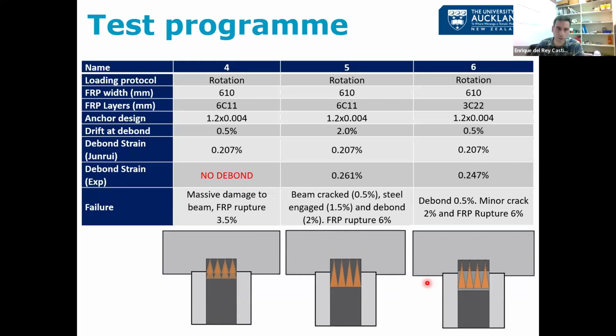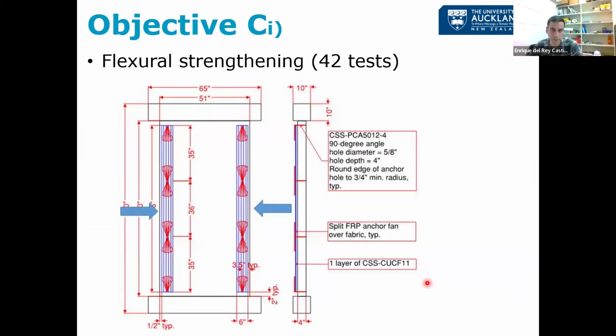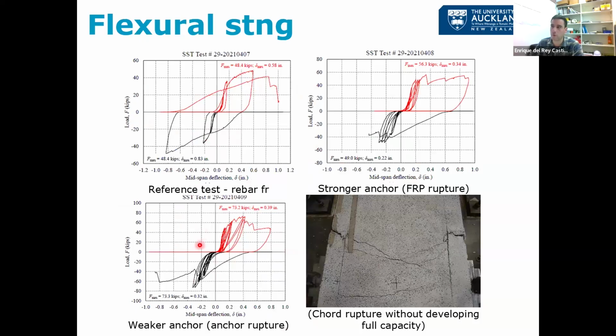Then we are leveraging some tests that have been done by our partners overseas on flexural strengthening of slabs. So these are, from the top of my head, I think they are 4 meter long slabs that were strengthened in flexure. So the flexural steel is not enough, and we are applying FRP, different anchorage configurations, 42 tests. And basically, this is giving us an idea of how we can increase the moment capacity of that slab or of that diaphragm without compromising the ductile response. We don't want to increase the force, the moment, but then have zero ductility, a very brittle response from the floor. That will not be very beneficial.